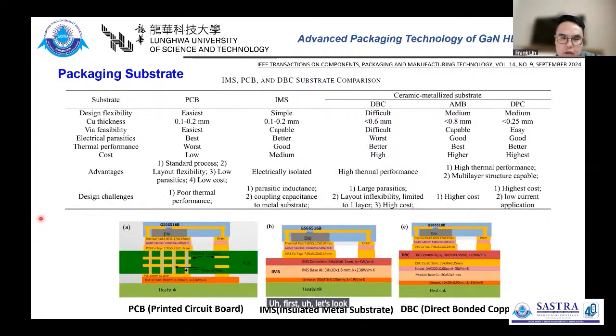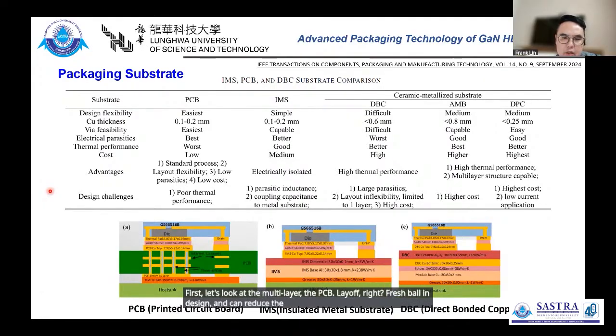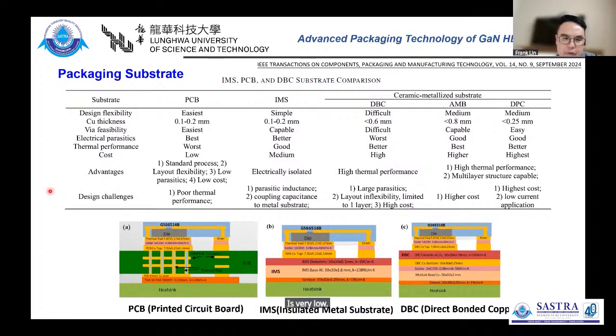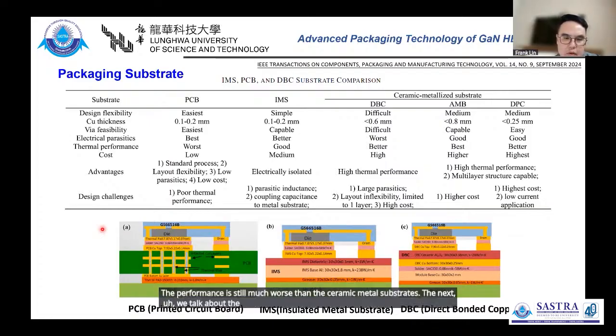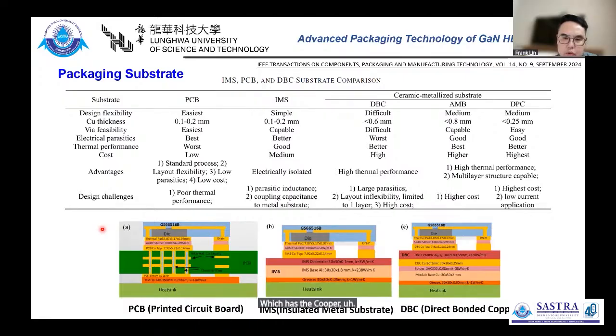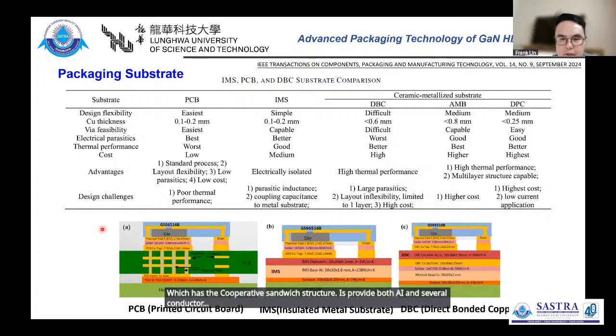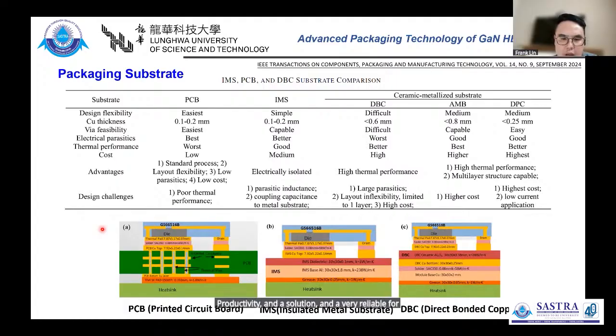First, let's look at the multi-layer PCB. They are flexible in design and can reduce the parasitic effect. But the thermal conductivity is very low, only about 0.3 watt per meter-kelvin. So the heat dissipation is limited. Even with thermal vias or copper inlays, the performance is still much worse than the ceramic and metal substrates. And next, we talk about the DBC, which has the copper-ceramic-copper sandwich structure. It provides both excellent thermal conductivity and isolation, and is very reliable for handling high current and high voltage.